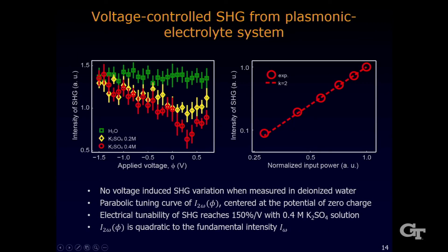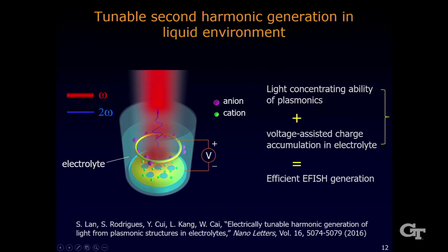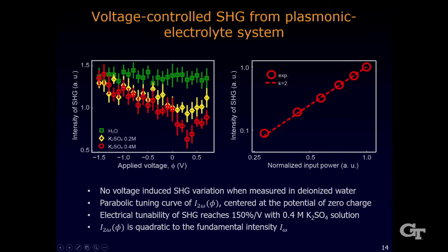So this is the major result from the experiment. Basically, we apply the electric potential to this electrode, and see how the nonlinear optical generation would be affected by this behavior, because you know that this effective Chi2 response is enabled and therefore can be controlled by the electrical potential, because the electrical potential affects the ion accumulation on the surface, okay? So if you put everything in the DI water, there's no voltage controlled variation in the harmonic generation because there's no ions in the DI water, okay?